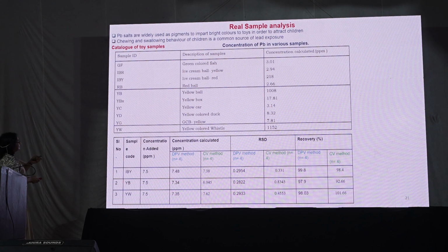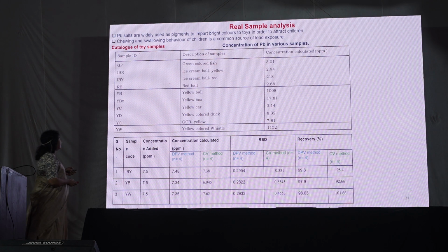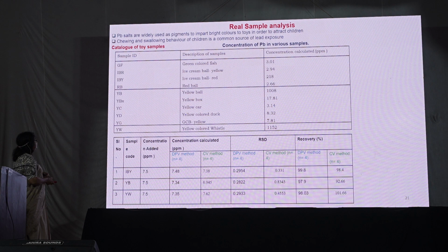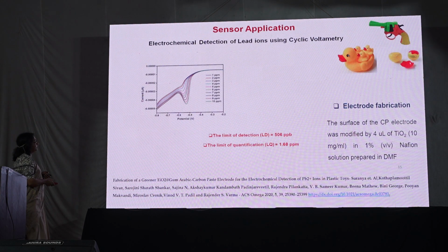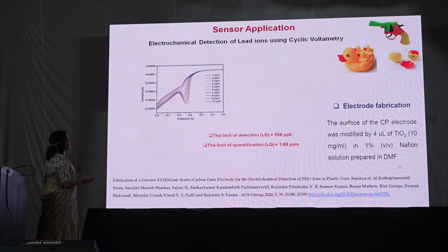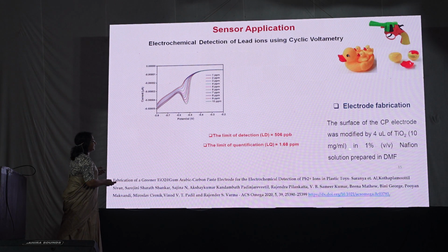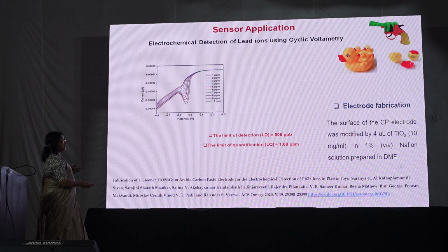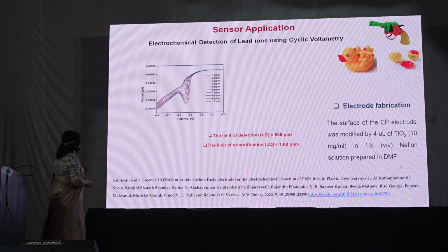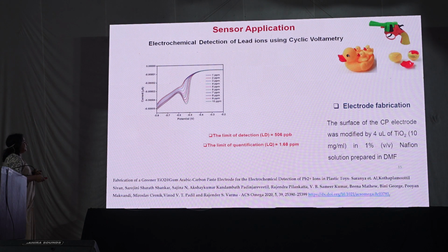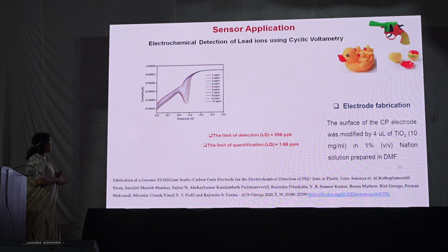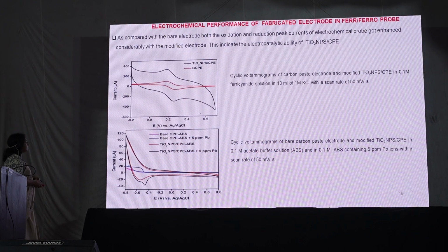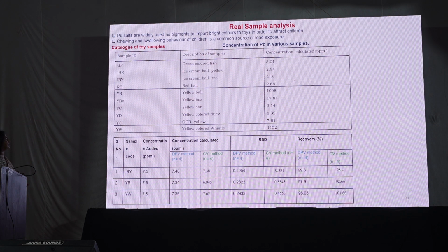We collected different samples from the locally available market, and we determined the amount of lead by using the carbon-based electrode modified with the nanoparticles. For the electrode fabrication, we modified the carbon-based electrode with 4 microliters of titanium dioxide with Nafion solution in DMF, and it is kept for drying. And this worked as a working electrode in the electrochemical workstation. We carried out the studies, and the results are compared with atomic absorption spectroscopy, AAS.